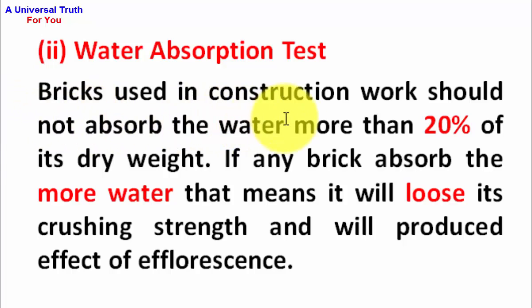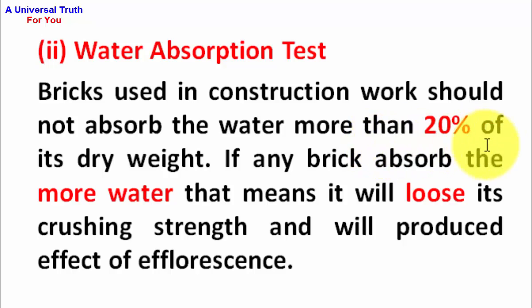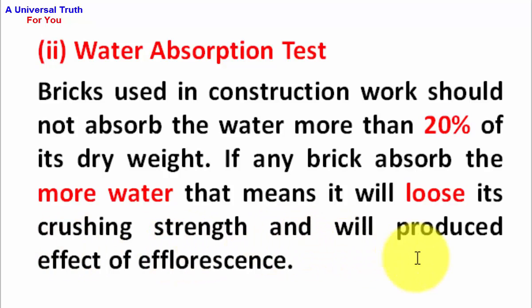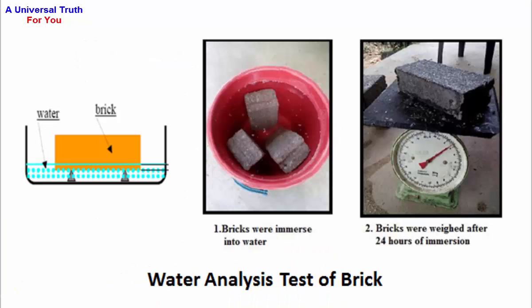Bricks used in construction work should not absorb water more than 20% of their dry weight. If any brick absorbs more water, it will lose its crushing strength and will produce the effect of efflorescence. This is the picture of the water absorption test of brick.